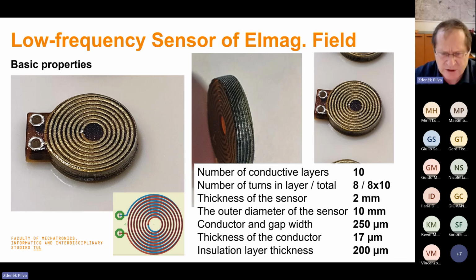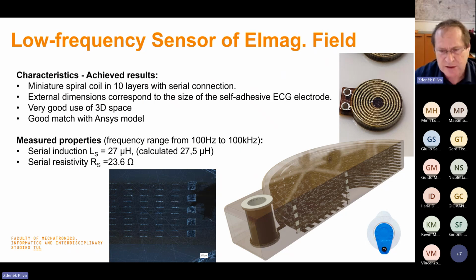The thickness of the sensor is 2 millimeters. It is composed of 10 conductive layers, and the insulation layer thickness is 200 microns. There are 8 turns of coil in each layer, and the thickness of the conductor is 17 microns. The coils in each layer are connected in serial. The external size of this sensor is the size of self-adhesive ECG electrodes, because we would like to implement it in this technology, in these standard sensors, and make some measurements on the human body.